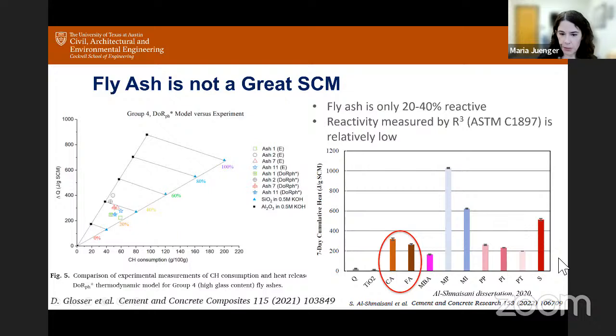The plot on the right comes from one of my former students' work, Saif Al-Shmaisani. He finished his dissertation in 2020. This is using the R3 reactivity method that's used to assess the reactivity of SCMs, and I'll go more into that later. If you look at this plot, CA is a C fly ash and FA is an F fly ash, and compared to other materials that were tested, it's not the best. We'll take these data apart later. But when we're trying to replace fly ash as an SCM, the bar is low in terms of performance. We're not trying to replace a great material with a great material. We're trying to replace a mediocre material with a mediocre material. And that's promising in terms of evaluating sources.